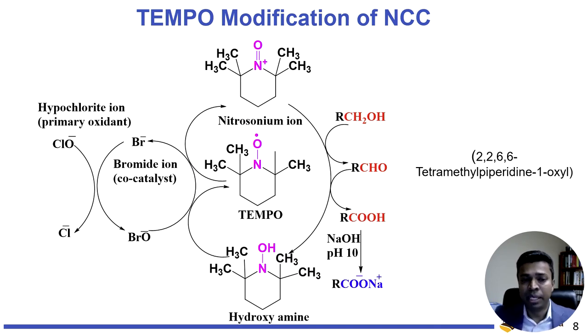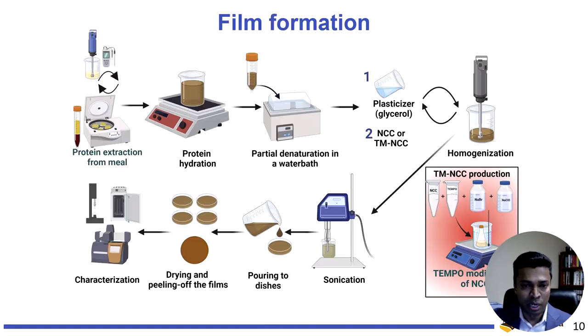So what we did in this particular research is try to modify the nanocellulose by oxidation using TEMPO-mediated oxidation, tetramethylpiperidine oxyl compound, and create more carboxylic groups in the nanocellulose. What this does is convert the hydroxyl groups on the nanocellulose surface into carboxylic groups with a higher surface charge. So this modified nanocellulose will now repel each other because of the increased negative charge.